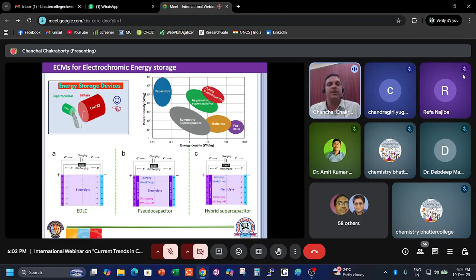So in this concept, we developed one metallopolymer. That metallopolymer has iron as the electrochemical center, meaning the redox active center. But what we did, we produced this ligand keeping in mind that we cut down the conjugation there. I told earlier that this can block the electron transfer between the iron centers. So self-bleaching can be restricted, and that can probably give better data in the discharge time. So basically the discharge time in that energy storage will be a little bit higher.